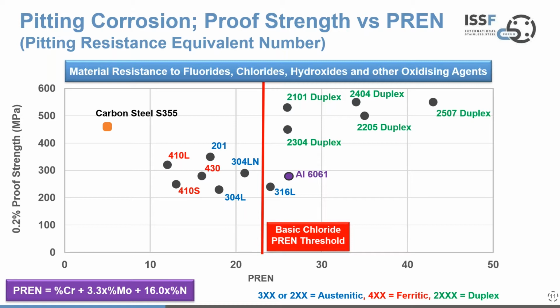And then in the middle section, either side of the red line, you have the ferritic, austenitic groups, and aluminium thrown in just for another comparative material reflection in there. But what becomes interesting when you look at this middle group is that the 316L grade is just to the right of that threshold line, and that's a grade containing molybdenum. So molybdenum is known to resist pitting corrosion, and this is a feature of the duplex grades as well. So some stainless steels do not perform as well against certain types of corrosive environments compared to others, and that's an important piece of understanding. So I just wanted to set that out using this slide for clarity.